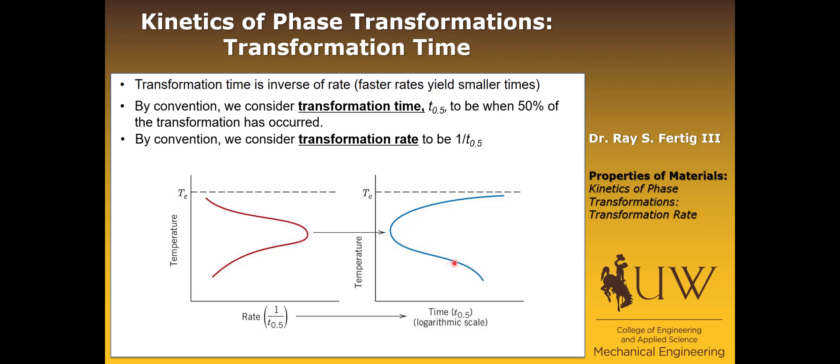the reaction or the transformation takes longer and longer. So this nose occurs wherever the transformation is fastest. It's also characteristic of these diffusion-mediated transformations, at least in these solid phase transformations.